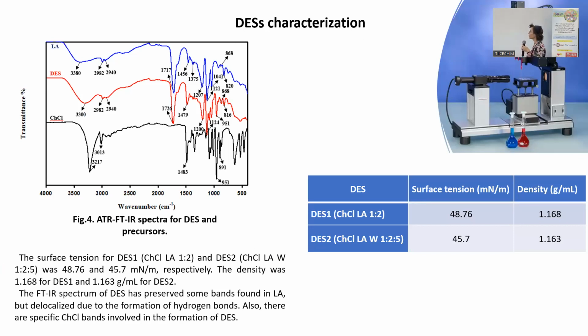For this characterization, we use FTIR, Fourier transform infrared spectroscopy. The spectra of this DES present the bands which correspond to lactic acid that were preserved in the DES, but with some shifted due to the formation of hydrogen bonds. Also, there are specific choline chloride bands involved in the formation of this DES. Compared with water, the surface tension of this DES is lower, and the densities are higher due to the formation of hydrogen bonds in the structures.